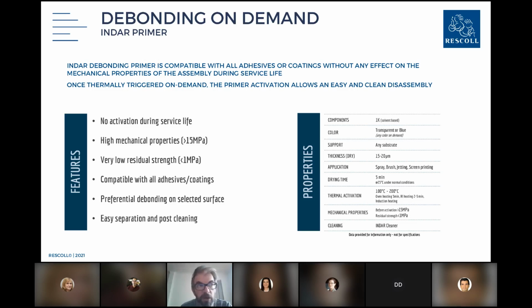For coatings, it's even more interesting because we are offering very high adhesion strengths. It's compatible with all adhesive or coating types, and you can select the surface you want to debond. In case of stripping, it's quite interesting because you can have a selective stripping based on the location, for strippable coating. And for the post-cleaning, you will see that it's very easy. It's a one-component solvent-based primer so far, and we can work later on a water-based version. Dry thickness is 15 to 20 microns, a typical thickness range of any paint. Application is quite wide because it can be spray, brush, automatized spraying or screen printing. Drying time can be reduced to below 1 minute with IR lamps, and thermal activation is in the range I just mentioned before.